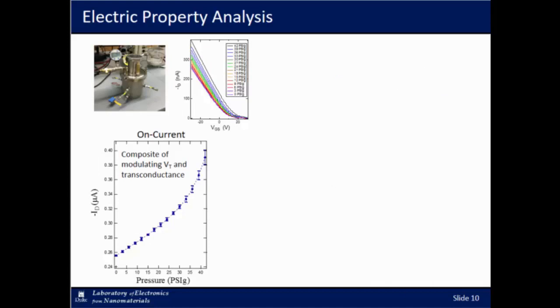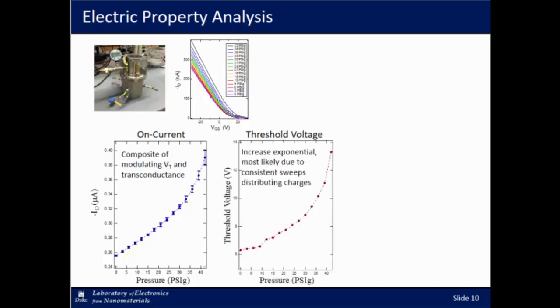And what we see is increasing, looks fairly linear for the first part of the pressure, and then exponentially increases. But this is a composite of two different electric parameters, the threshold voltage when the device is turning on, as well as the transconductance. So we pulled those out separately. The threshold voltage has a similar look and increases exponentially with pressure. But if you remember, we started our test at 42 psi and ramped down to 0. And the decrease as the number of tests increases is pretty common when you're sweeping a transistor over and over, that threshold voltage will reach an equilibrium. So we think that this is not due to pressure, that it's due to threshold voltage equilibrium, and we could see that as we did hysteretic sweeps.